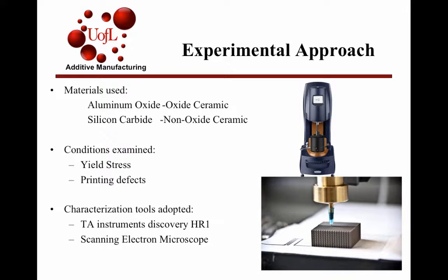The materials used were aluminum oxide for the oxide ceramic and silicon carbide for the non-oxide ceramic. The specific conditions they looked at were yield stress and the printing defects. For the yield stress, they used a Discovery HR1 testing machine, and for the printing defects, they looked at it with a scanning electron microscope and just visually inspected and looked at what they saw.